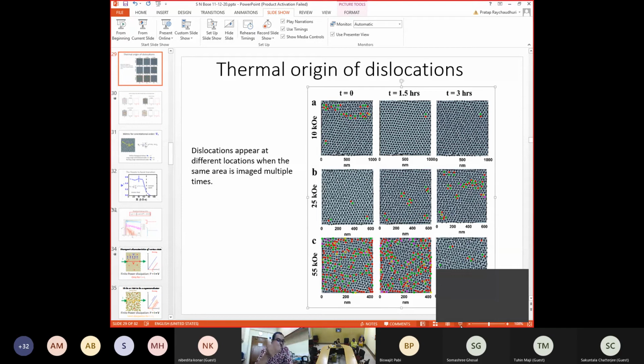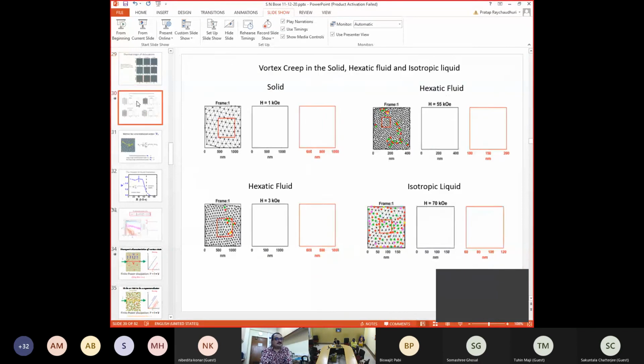The question is, since you are also doing the time measurement, is it possible to look at any dynamical correlation, for example? Yes, that is something on the cards, but we have not done it yet. The problem is that STM is actually a slow measurement. These snapshots are taken at 15 minutes interval, and we are joining the points. So we can only look at slow dynamics. We cannot look at fast dynamics.